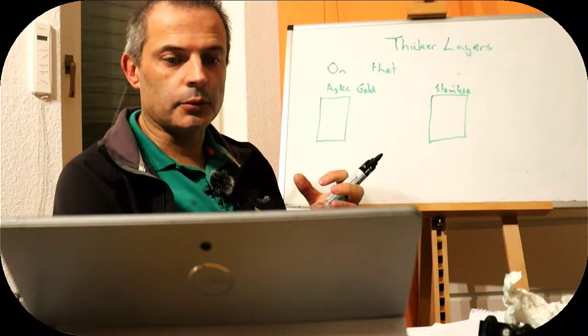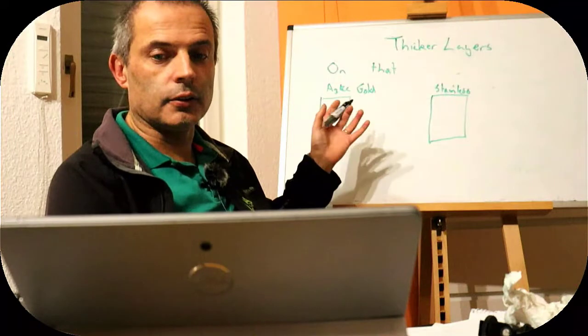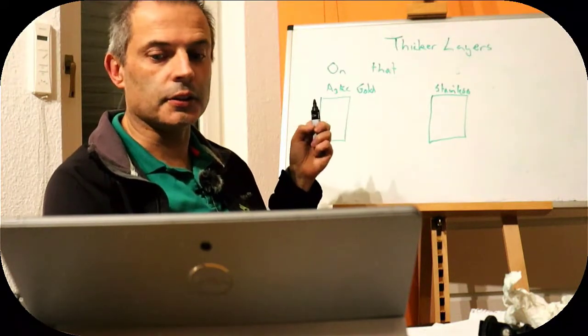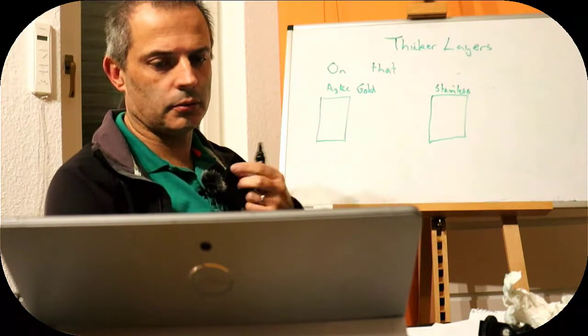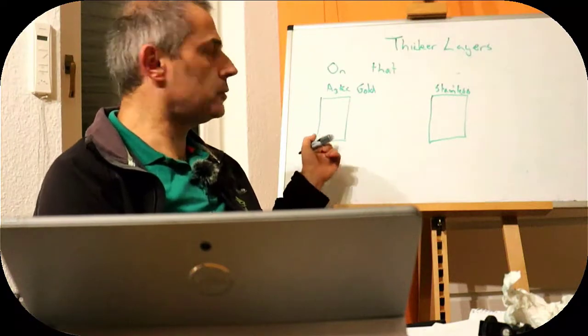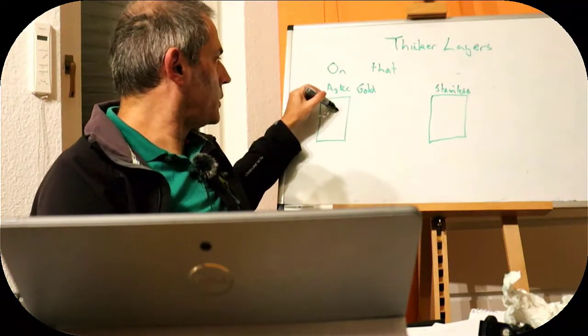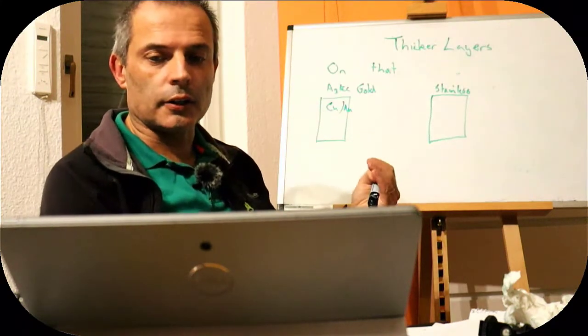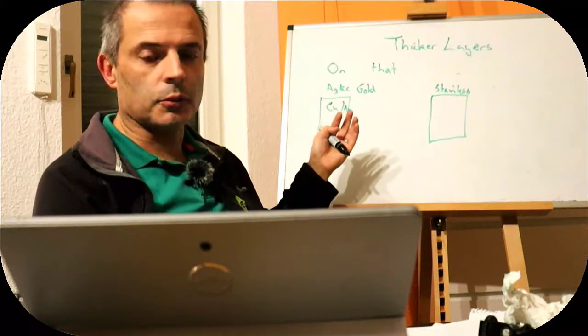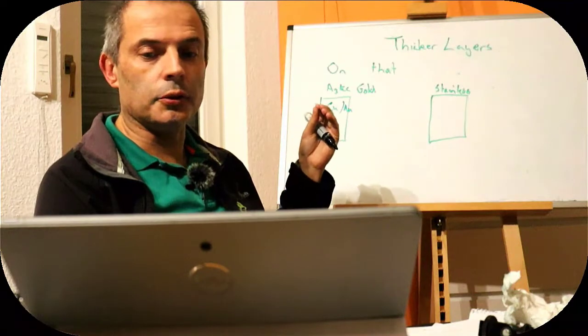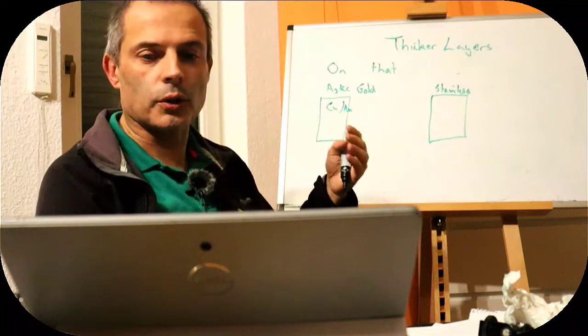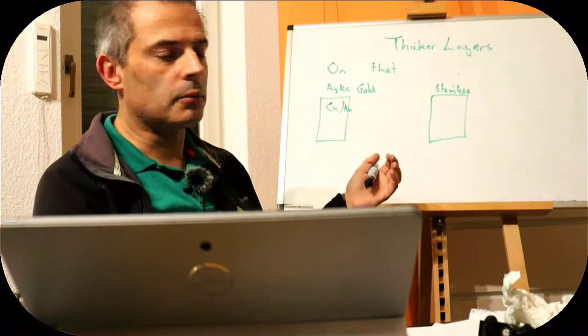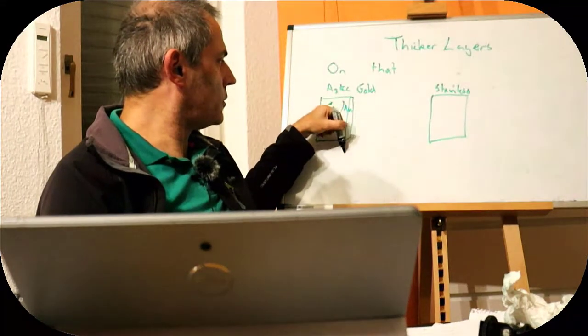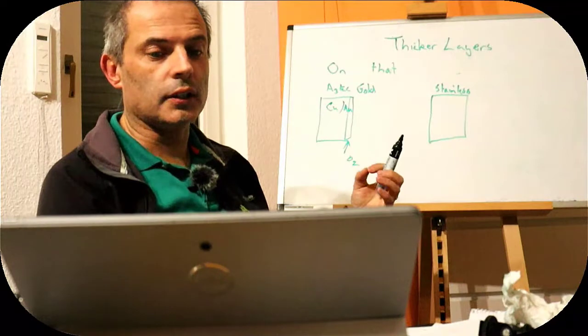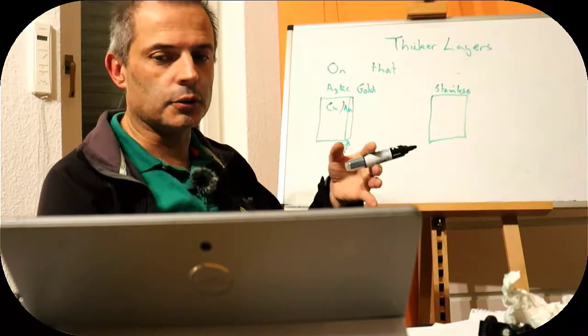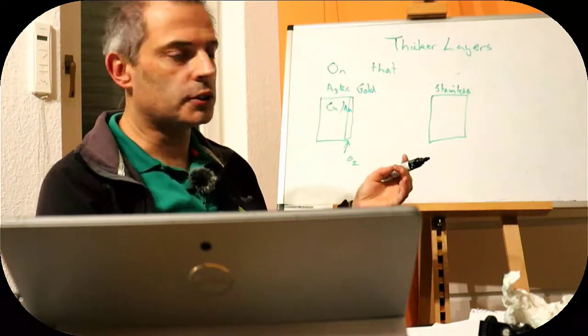While we are talking about that subject, we should probably mention another thing, which is the effect of diffusion and alteration in the surface on diffusion. So if we take something like Aztec Gold, which is mostly copper with a little bit of gold in it, that is how they used to make their large statues. Take some copper, add a little bit of gold, and then you follow a process. Their process was to take the copper and gold and heat it up. If you heat it up, the copper mostly reacts at the interface with oxygen, and because the gold is gold, it's not very motivated to do that, so the copper diffuses out, leaving a layer just below the surface which is rich in gold.